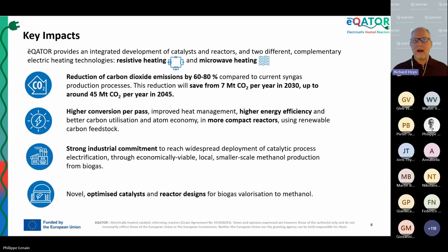So the key impacts of this, as I mentioned, the steam reforming of natural gas to make methanol has a very high CO2 footprint. It's about 10% of the CO2 emissions from the chemical industry, and we expect to save 60 to 80% of the carbon dioxide emissions from that methanol synthesis with our technology. We expect around 7 megatons of CO2 per year saved by 2030, and up to around 45 megatons CO2 saved per year at 2045. Because we're doing this electrically, and as has been commented before, we expect higher capacity conversions, we expect more compact reactors, we expect higher energy efficiencies, and we have these novel optimized catalysts already in-house for this biogas valorization to methanol. Next slide, please.